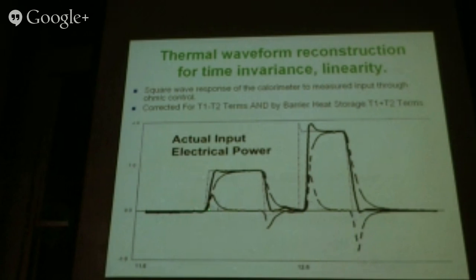So for example, the Japanese at ICCF7 had just given up. I think this was at Technova, on doing cold fusion with Fleischmann and Pons. And I spoke to them, I said, why? And they said, well, we have one calorimeter that shows excess heat and one calorimeter that doesn't. And I said, well, can I see your calibrations of the square wave? And they were very nice. They showed it to me, and the one that didn't show excess heat showed singularities.